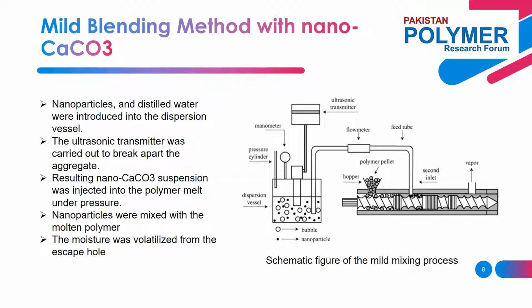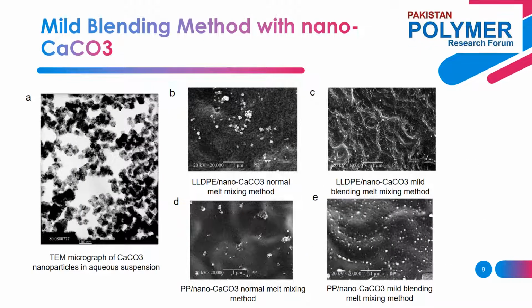The nanoparticles were mixed with the molten polymer and transported ahead. Then the moisture was volatilized from the escape hole, and the nanoparticles were held in the matrix at the primary diameter as in the suspension. The extrudate was then pelletized. After drying to remove the moisture attached during extrusion and pelletizing, the pellets were injected into both dumbbell tensile samples and impact samples. A transmission electron micrograph of the nano calcium carbonate suspension is shown in figure A.